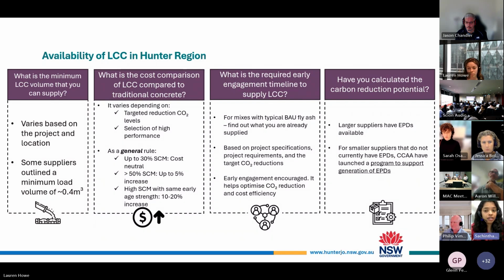And then we asked their preference on early engagement to provide low carbon concrete. For a lot of suppliers, they have fly ash in their mixes by default, so they don't need early engagement. But as councils, you need to be aware of whether your supplier is already replacing cement with fly ash or not. So for councils, you need early engagement. And for the mixes that you want with an increased amount of SCMs by adding slag into them, the early engagement will be based on project specification, requirements, and targeted carbon reduction.